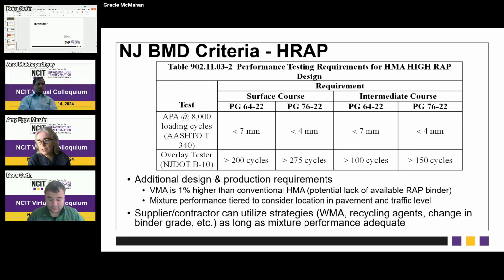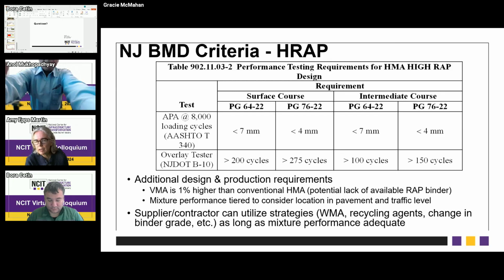So their current criteria shows both a rutting test, which is the asphalt pavement analyzer, and an overlay test, which is the cracking test. And it depends on whether they're at the surface, which most of the BMD efforts right now are focused on the surface. And it also depends on what binder grade they're using. The 64-22 is an unmodified binder grade, and the 76-22 is a polymer modified binder grade. And so they have both ends of the spectrum, the rutting end and the cracking end.